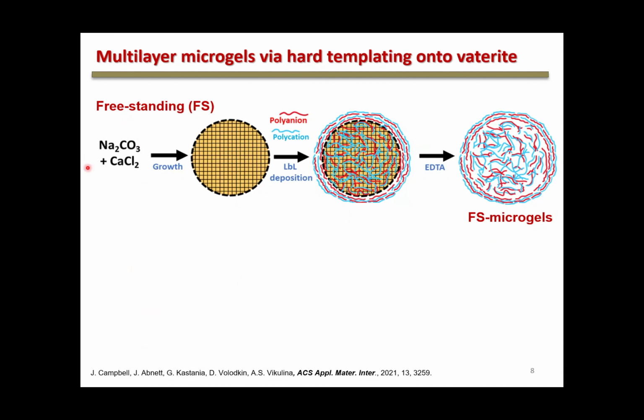So you first synthesize calcium carbonate. That may be a very simple synthesis by mixing two salts at specific conditions, concentration and stirring speed and so on. So you get the spherical calcium carbonate particle. And then you coat it with multilayers. I think most of you, or at least many of you who are now in the room, are familiar with the multilayer coating. But for those who are not familiar, let me just explain. You simply adsorb polyanion and polycation in a sequential manner on the surface and inside.